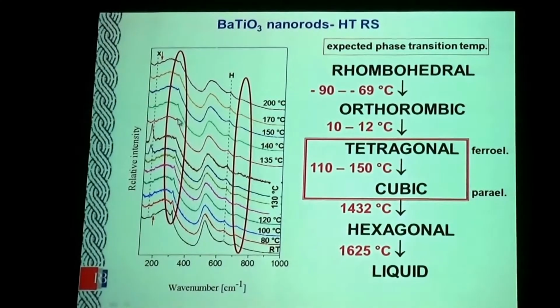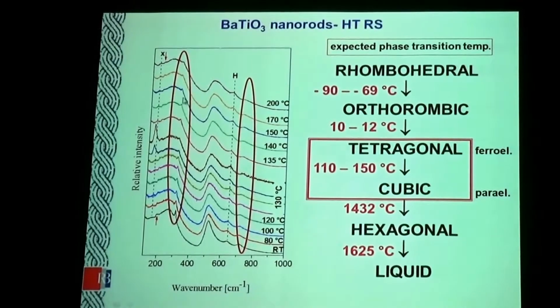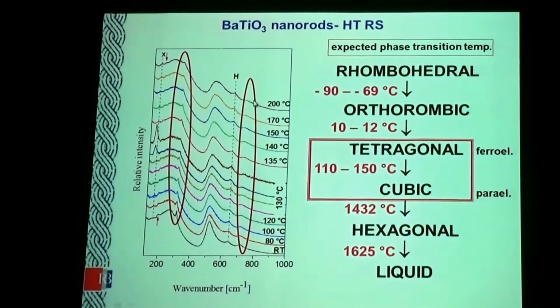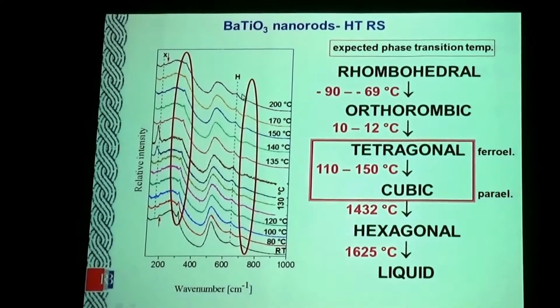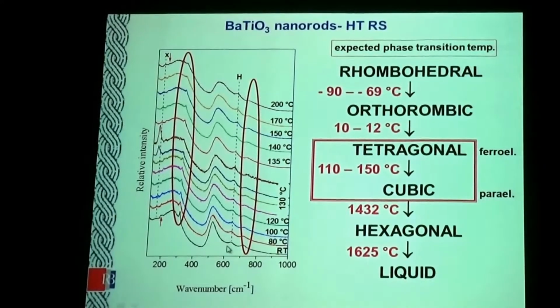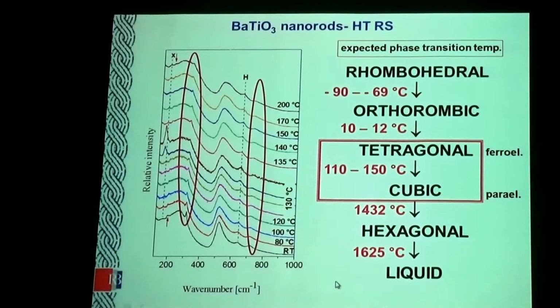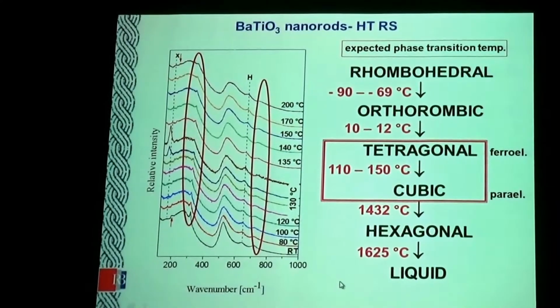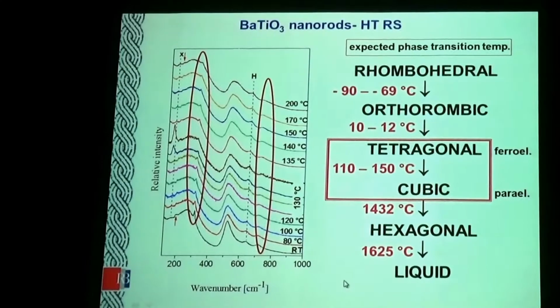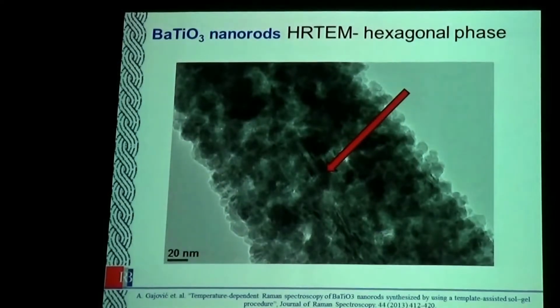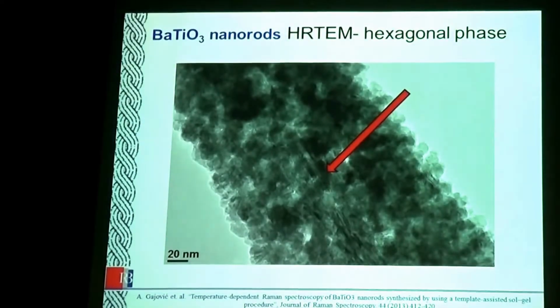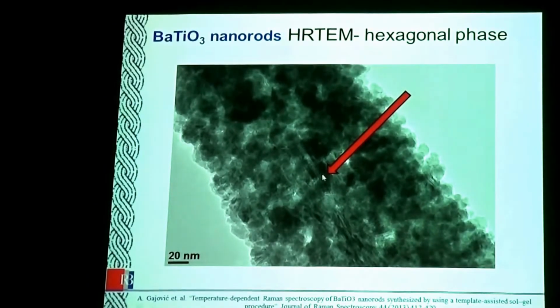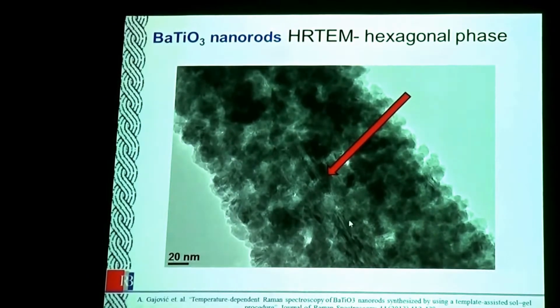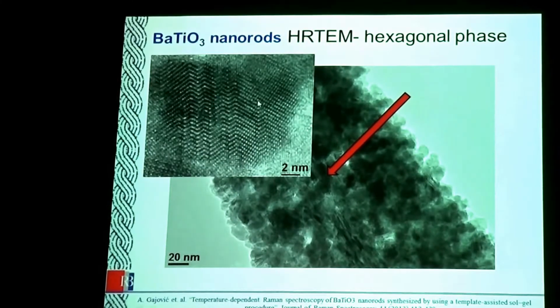We observed both bands which belong to the tetragonal structure at much higher temperature, but this hexagonal band was still here. Somebody could say maybe this was a mistake, maybe it wasn't a hexagonal structure. But later on, high resolution measurement was done, and some kind of lamella was observed in our nanorods, and this lamella was really in hexagonal structure.